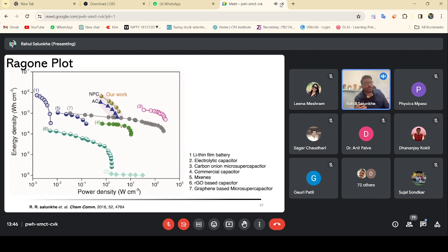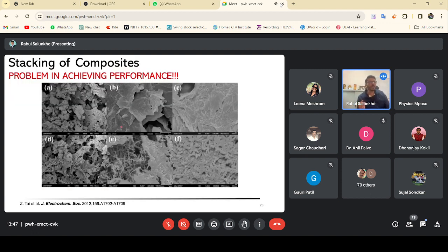Although this kind of activated carbon has a micropore structure of around 74%, still these carbons have very limited conductivity, and because of that our material has shown comparatively higher performance than that of the activated carbon materials. Now another important problem was stacking of the composite.